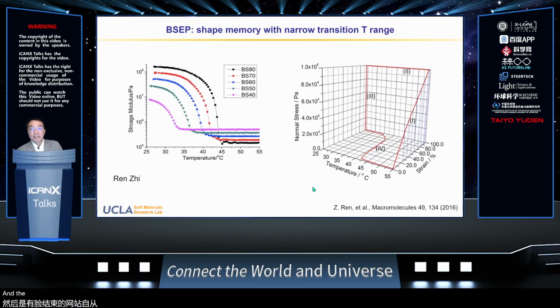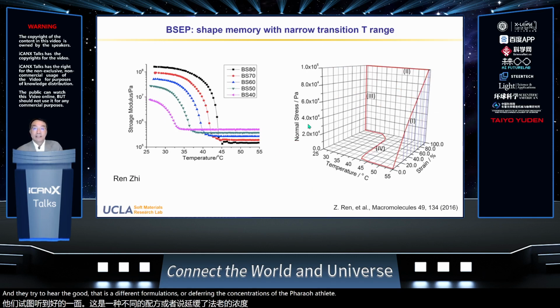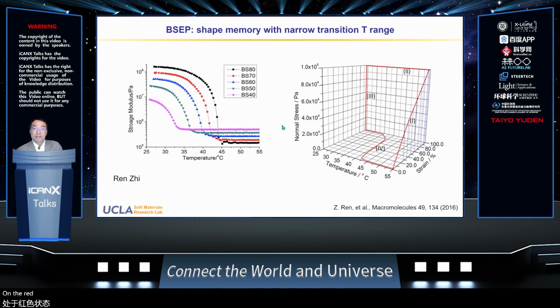The chart to the left shows different formulations, or different concentrations of the stearyl acrylate. Let's look at the blue one here. It contains 60 weight percent of stearyl acrylate. We see that around 40 degrees Celsius, the modulus varies by 3 orders of magnitude within a temperature range of 5 degrees C.